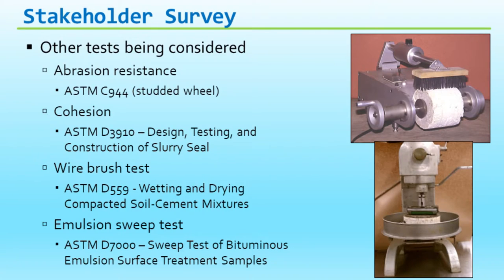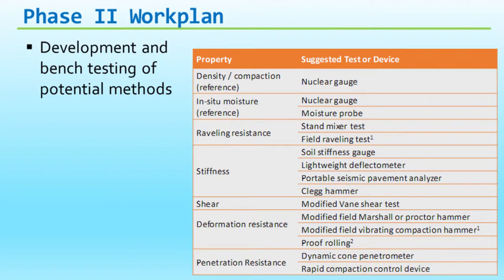Wire brush test, so the wet and dry cycle test for cement stabilization. We've looked at some adaptations of that. That has been reported. And then the emulsion sweep test as well for coming up with some basic performance parameters. So all of those have been out there. Wide range of experimentation. But again, when it comes down to the nitty-gritty, it's pretty much moisture and density. So at the end of all of that, we put together a work plan to say what are we going to look at in phase two? So that was the table from the report. So density and compaction, it's really important to do that, but we need more.